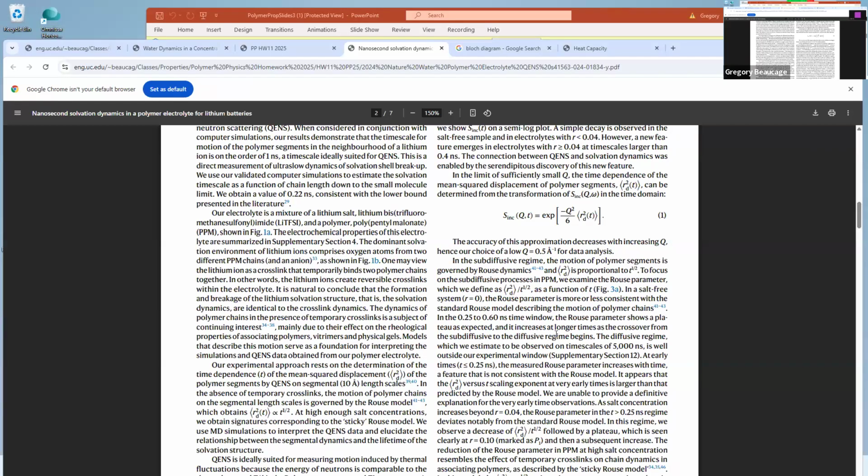You get smaller sizes at high Q, but he's saying 0.5 is a large size. And for the backscatter machine, it is large because it's going to go up to like 10Q or something, you know? So basically 0.5 is pretty small for him. It's big for us. Like for us, we're looking at 0.001 usually to look at polymers, 0.001 to 0.01, right? So he's looking at 0.5. It's much smaller. So he's at 10 angstrom size. He's saying that's 1 mer unit.